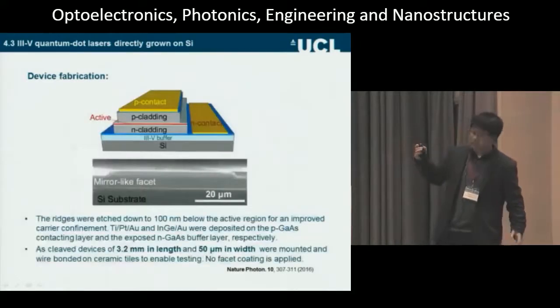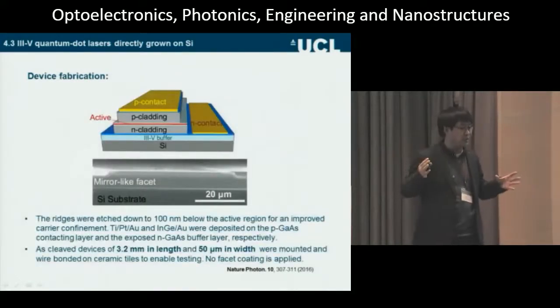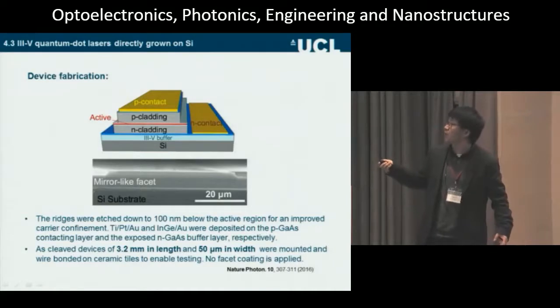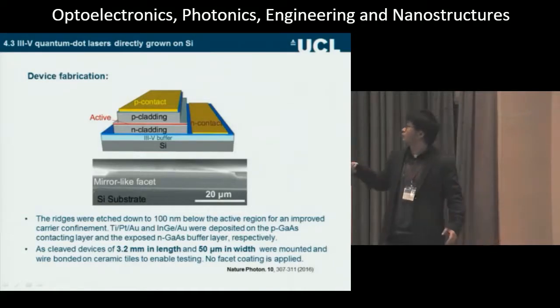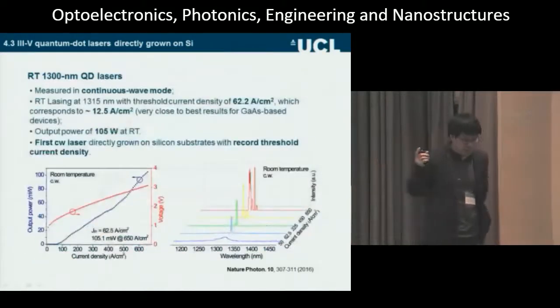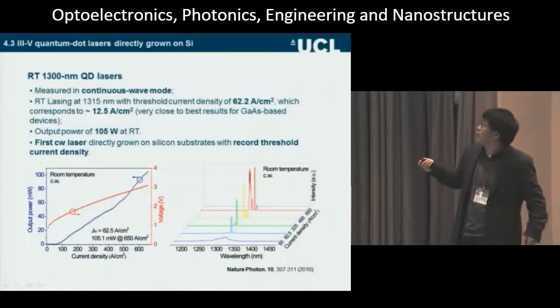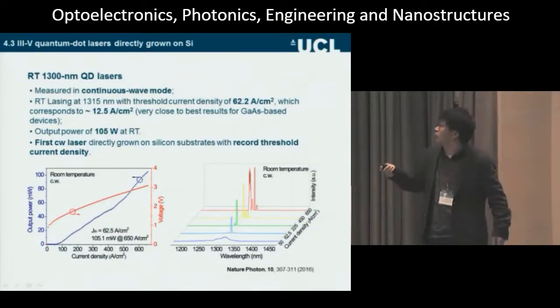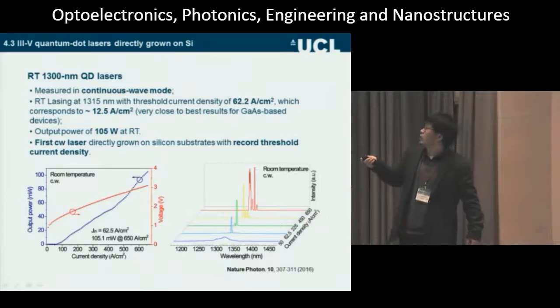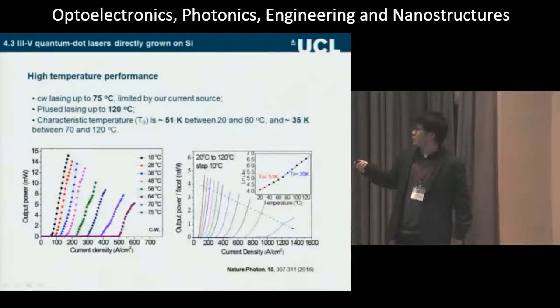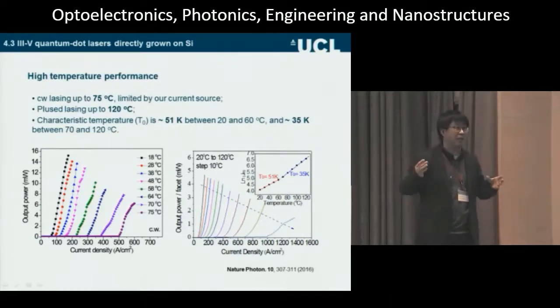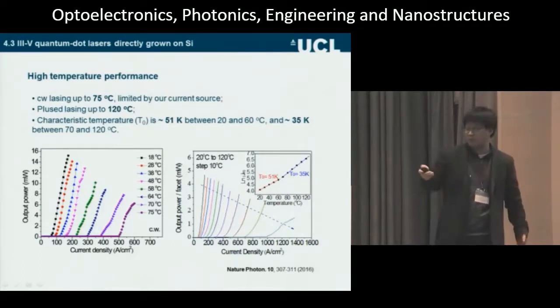At that time, we had 2 postdocs working on fabrication. We can get mirror-like facets and a top-to-top contact. For this one, we get the first CW quantum dot laser grown directly on silicon, with power over 100 milliwatts at 1.3 micron and a very low threshold. This laser operates CW up to 75 degrees and pulsed up to 120 degrees. All the measurements are limited by our setup. It's not a really limited device.